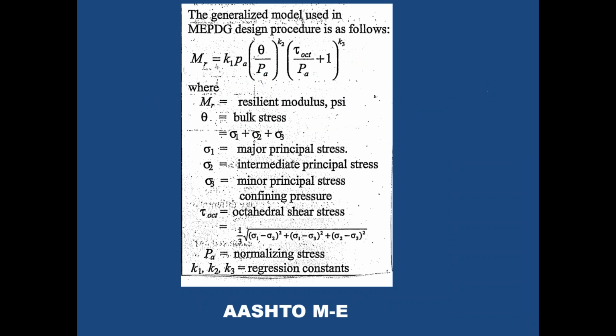Well, this is the generalized model that's in the MEPDG, the Mechanistic Empirical Design Guide, AASHTO-ME as it's now called. And notice we do have our theta value there. Also, this tau octahedral is a calculated value from an elastic layered pavement analysis program. So in this case, you still have to do your materials testing or assume some typical values for K1, K2, and K3 in order to make an estimate of the modulus.